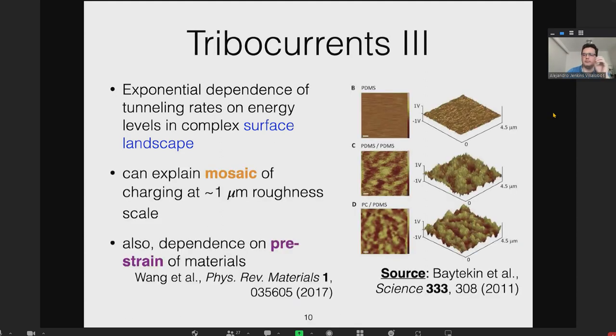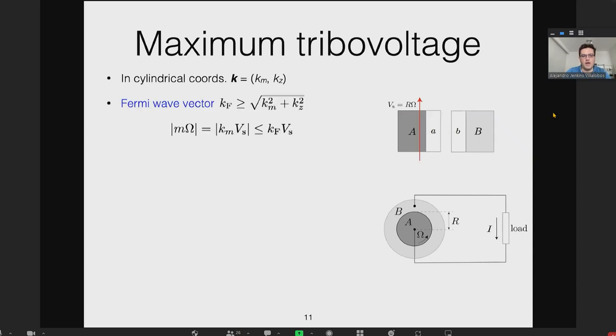Professor Marx emphasized this last time: people used to talk about just the triboelectric series, but we know triboelectrification is not entirely a materials process. This is consistent with this description. I don't attempt to calculate those couplings, but the surface of a solid is a very complicated landscape with energy levels varying over it. There's an exponential dependence of tunneling rates on those energy levels, so over the landscape of roughness there'll be regions where current flows one way and regions where it flows the other way. The triboelectric series emerges only on average. Triboelectrification also depends on strain because strain affects surface electron levels.